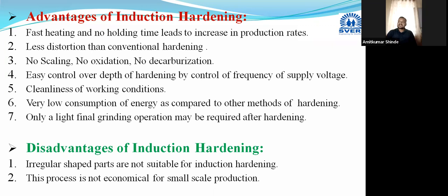What is the disadvantage of this method? Induction hardening cannot be done if the component has an irregular shape or a complex shape. We cannot do the induction hardening on it. And if we are using this induction hardening for mass scale production only, then and only then it is economical. Otherwise, it is an uneconomical method.